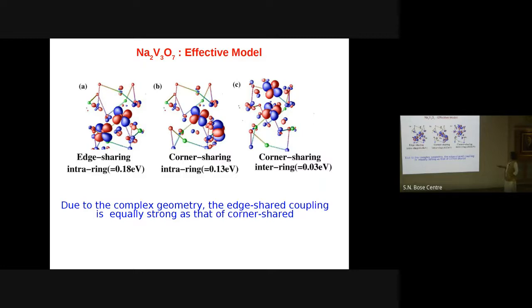Within the ring, there are 2 kinds of interaction. One is edge sharing, that means 2 vanadium pyramids, they are connected to each other by 2 connecting oxygen. These are called edge sharing. Other is corner sharing, they are connected to each other by 1 sharing oxygen. And because of this complex and very distorted geometry, it turned out that both edge sharing and corner sharing interactions are almost of similar strength. The interaction between the rings turned out to be an order of magnitude smaller, as kind of expected.